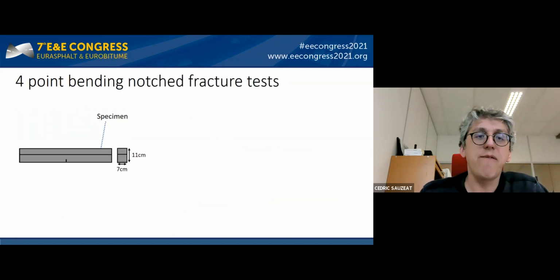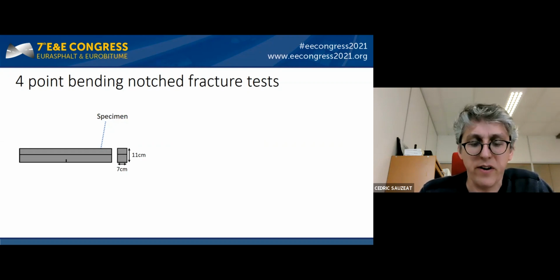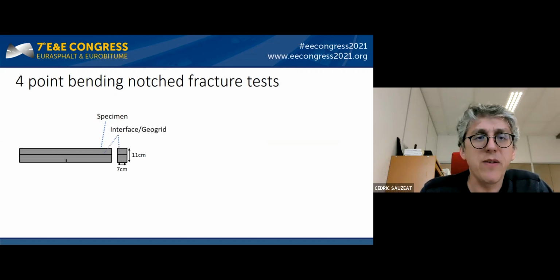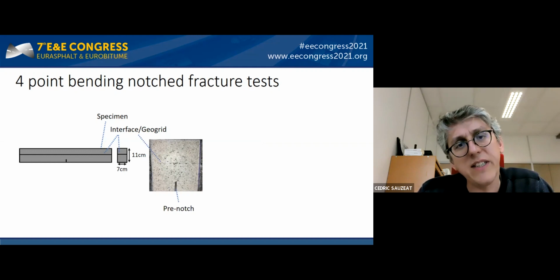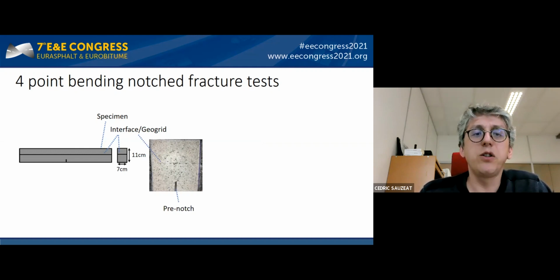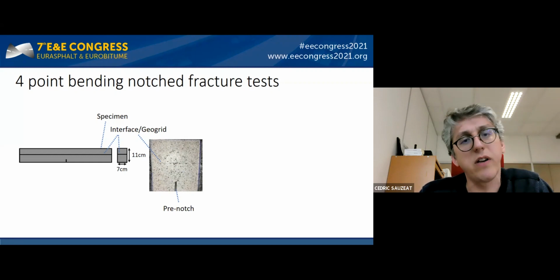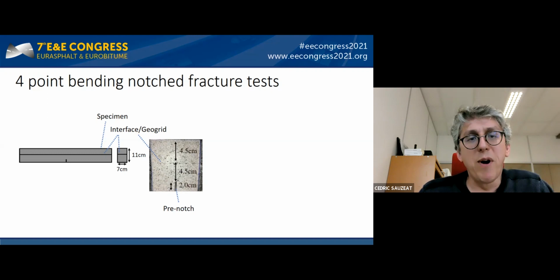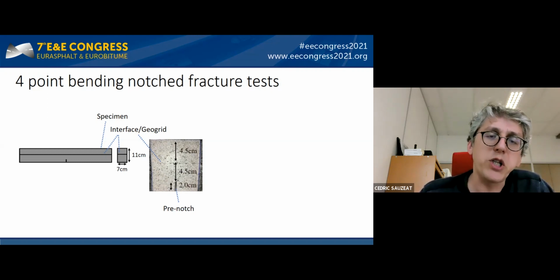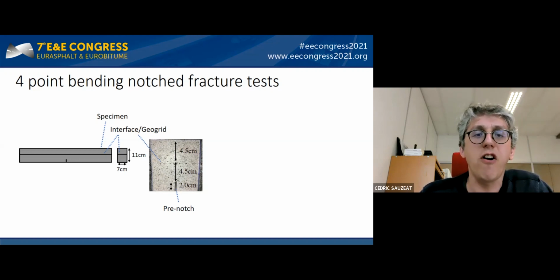From this slab, we have cut the rectangular specimen. You have here the scheme of this specimen. You can see the interface geogrid. You can see here the central part, and the specimen was firstly pre-notched at the middle, at the center. The notch was 2 centimeters deep, and above the notch, you have 9 centimeters of materials, and the interface was just at the center.